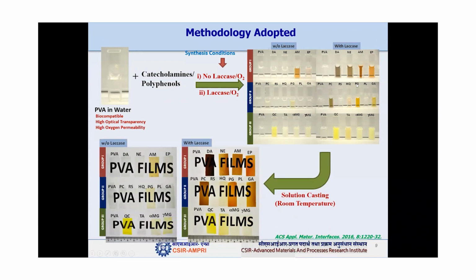And you can see these are the films we have designed by using this methodology. And I think you can easily see the difference between these two films. This is without laccase, so in only a few of the films you can see some color, but in the case of films with laccase, you can easily see the brownish or yellowish color in the films, which is actually because of the polymerization of these polyphenols and catecholamines.